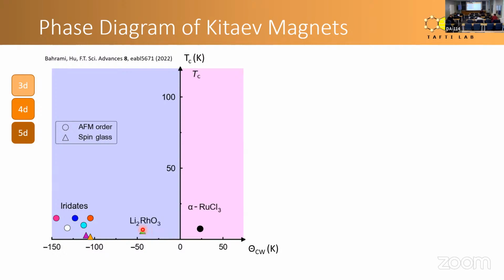Now, here is lithium rhodate, the material that we wanted to exchange and study. Basically, the idea was that when we exchanged the iridate materials, we saw that TC always goes down. And so we wanted to exchange lithium rhodate, which already has a very small TC, and basically bring the TC to zero, if possible, and realize a spin liquid material. But like many good ideas, it actually went quite wrong. So the experiment went totally the opposite direction.